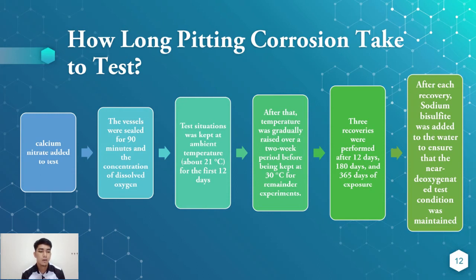Celsius for the first 12 days. After the first 12 days, the temperature was gradually raised over a 2 week period before being kept at 30 Celsius for the remainder of the experiment. Three recoveries were performed, after 12 days, 180 days and 365 days of exposure. After the recovery, sodium bisulfite was added to the water to ensure that the near deoxygenated test condition was maintained.